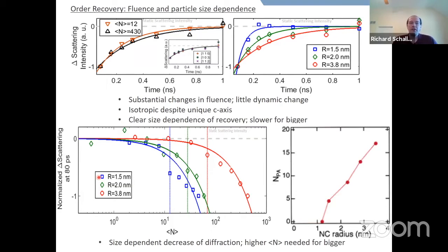If you look at the total scattering, the changes that we can create, it's also true with scanning fluence. We can go to really low powers. We don't have infinite signal to noise with this method, so we don't see differences that are appreciable at really low powers. If you start integrating these signals and go up and up in fluence, what you see is that the smallest particles melt, or start to show disorder. Deal with the word melt later.